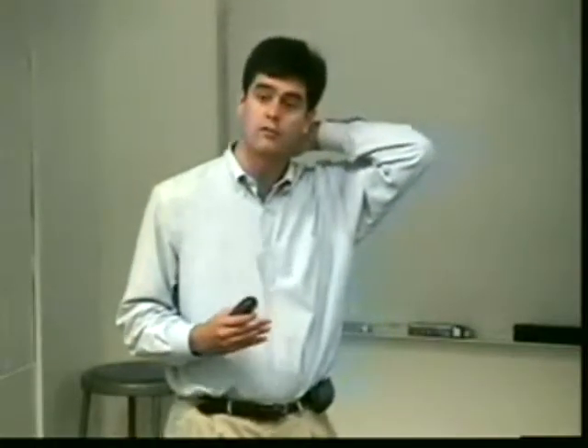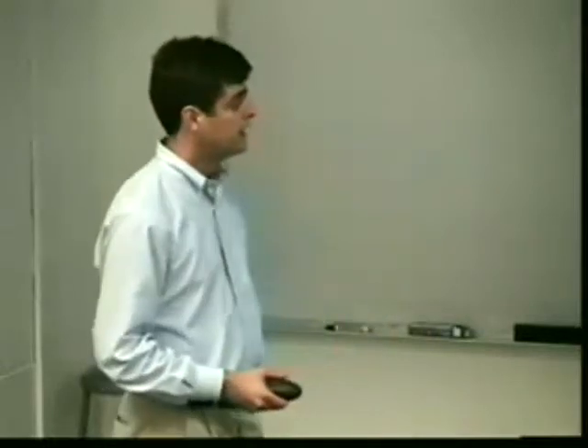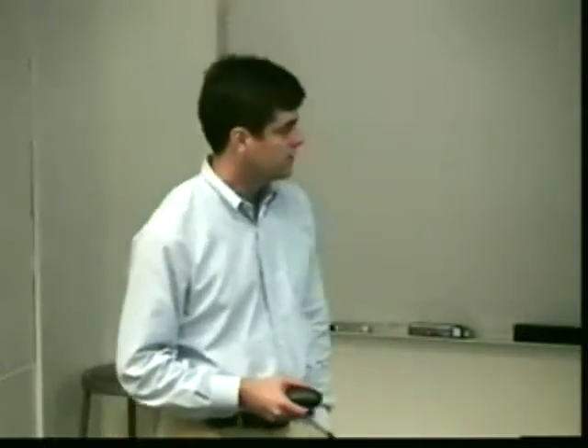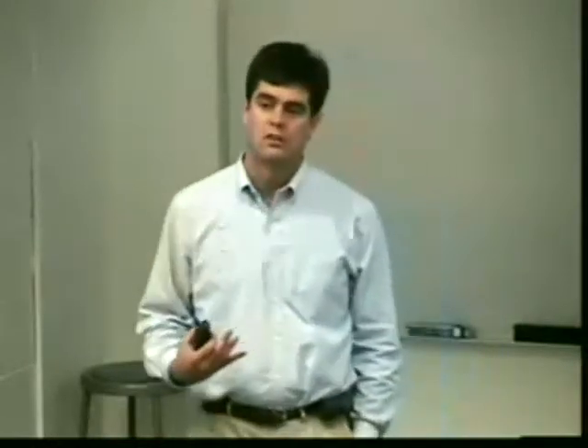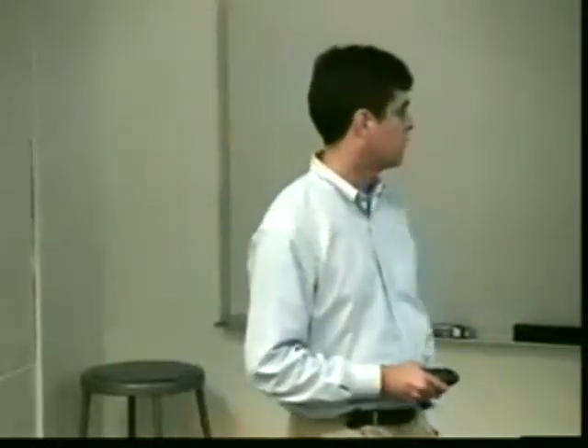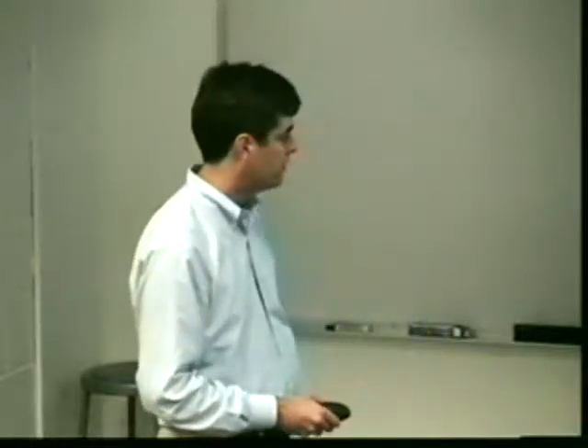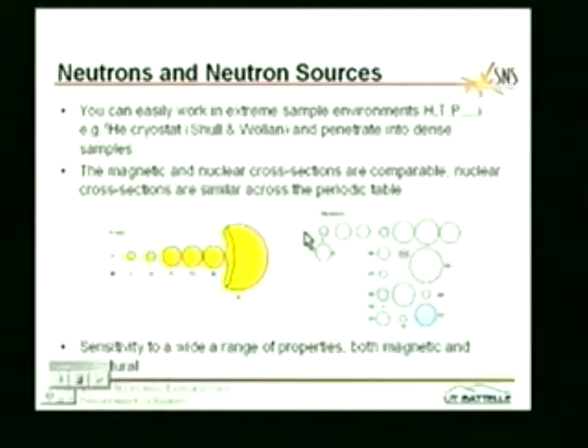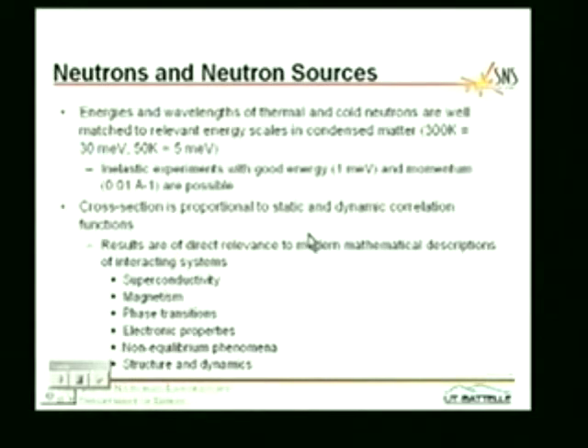So you can selectively deuterate and really enhance the sort of signals that you get to give you very specific, site-specific information about the structure. So overall, you have sensitivity to a wide range of properties, both magnetic and structural. I already mentioned that the energy of a thermal neutron is typically around 20 or 30 millivolts. If you take a cold neutron, then you're more like maybe 5 millivolts.